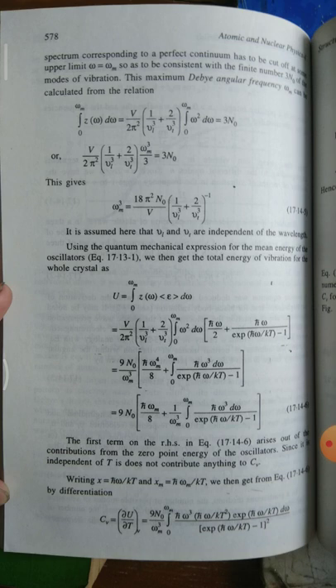Using the quantum mechanical expression for the mean energy of the oscillators, we then get the total energy of vibrations for the whole crystal as U = integration 0 to ω_m of z(ω) ε(ω) dω = V/2π² (1/v_l³ + 2/v_t³) integration 0 to ω_m of ω² dω [ħω/2 + ħω/(exp(ħω/kT) − 1)], which becomes 9N₀/ω_m³ [ħω_m⁴/8 + integration 0 to ω_m of ħω³ dω/(exp(ħω/kT) − 1)].